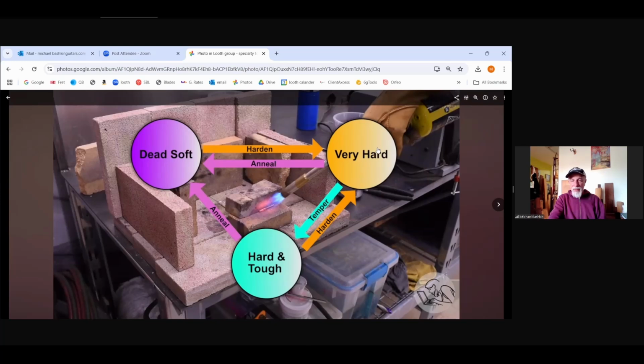And in this state, it is very hard, probably Rockwell 65 or harder, but it's also very brittle, and the tool is prone to snapping, breaking, chipping. So you want to do one more process called tempering, which is to heat the tool at a low heat. And depending on how hard you want to leave the tool, that temperature will vary a bit. And I'll go through that in a minute.